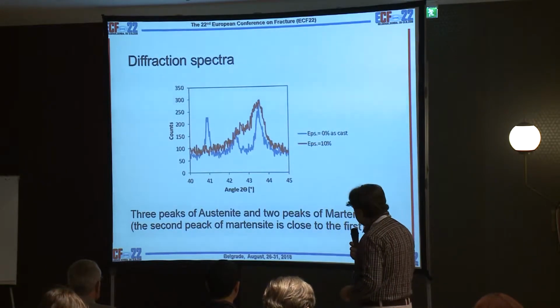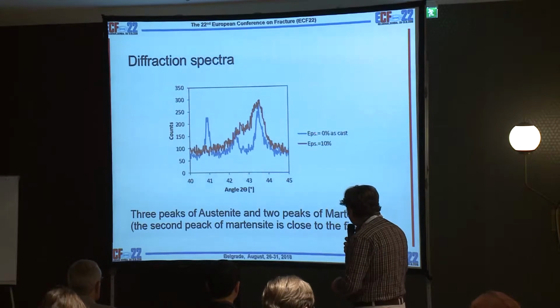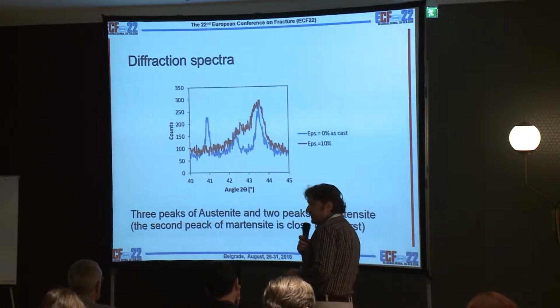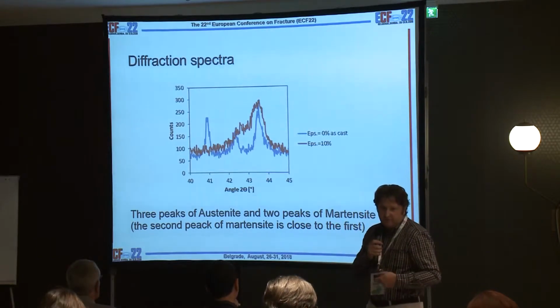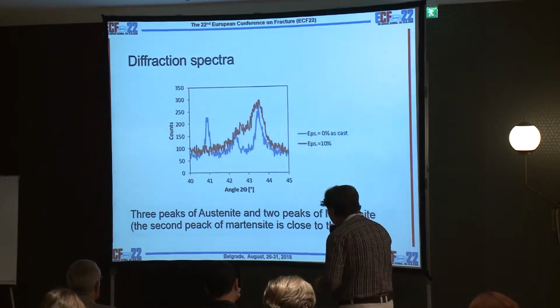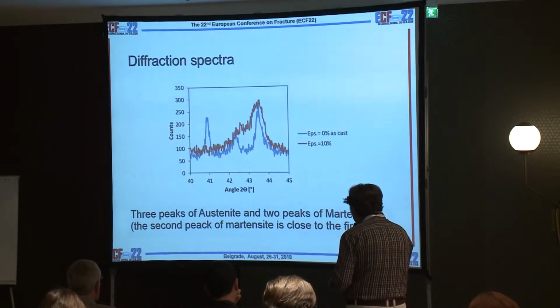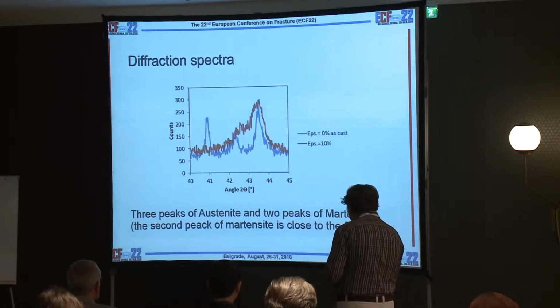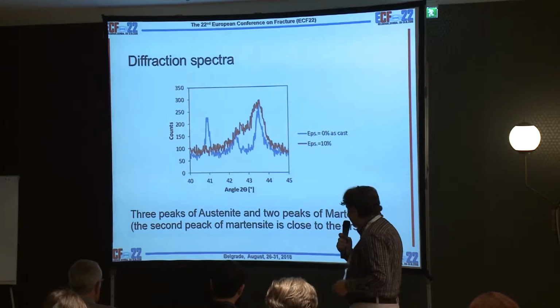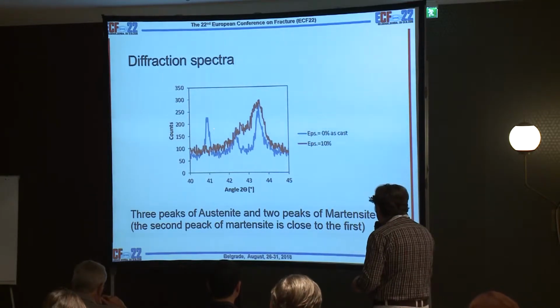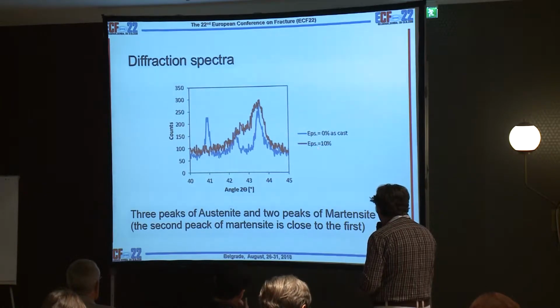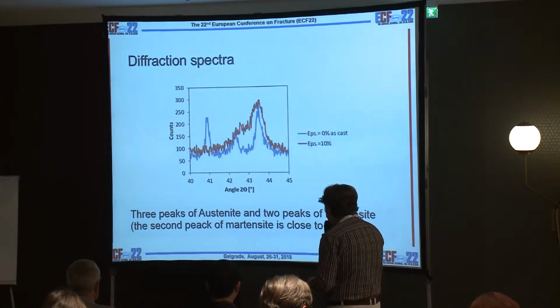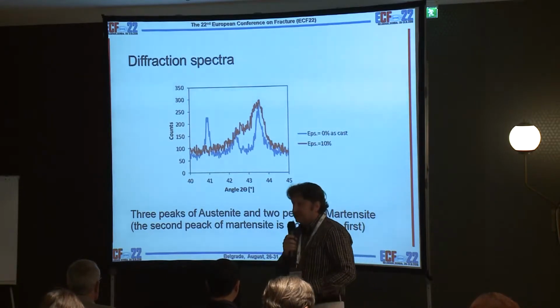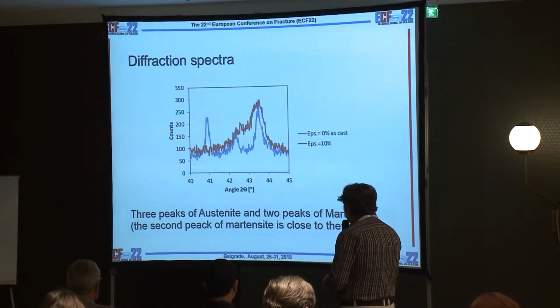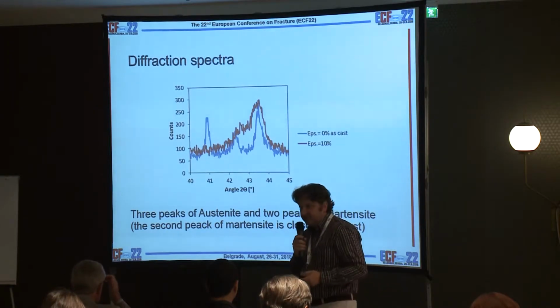So in terms of structure, here you can see the diffraction spectra. These are results of XRD analysis performed on the surface of the tensile test specimen. We can see in unloading conditions the presence of this peak at about 41 degrees. This is the angle 2 theta, the angle of diffraction. And this peak disappears when the material is loaded at high values of deformation. It is due to a change of structure, because the plane characterized by this diffraction peak disappears.